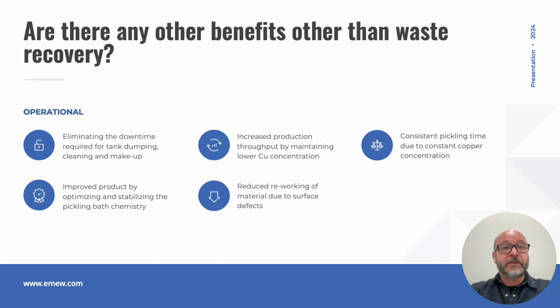Are there any other benefits other than waste recovery? Absolutely. From an operational perspective, the emew system offers many advantages, which would include eliminating the downtime required for tank dumping and makeup, improve product quality by optimizing and stabilizing the pickling bath chemistry, increase production throughput by maintaining a lower metal concentration, reduced reworking of materials due to surface defects when the pickling solution or etching solution gets out of specification, and importantly, a very consistent pickling time due to the constant copper concentration that's maintained and the constant acid concentration that's maintained in the pickling or etching process.